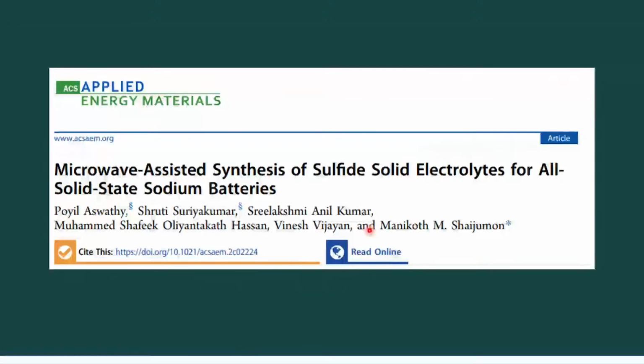But when I started working with it, we found that it was very air sensitive. I take it out of the glove box, it reacts spontaneously, and there was one more issue associated with sulfides. What is that? Chemistry? Sulfides? Yes? The smell. It is so smelly that people never allowed us to work in the lab, and we had to work at night time, and we had to protect it with Kapton tape. We had to seal it. We tried ball milling, we tried to seal it with Kapton tape, we tried to put it in a crucible and seal it with a cork.